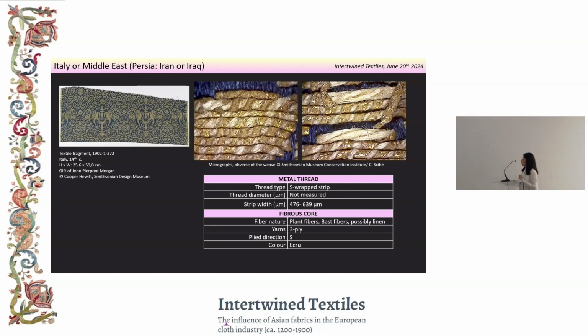So we have threads that are always made by metal in S-wrapped direction. So they were wrapped around a core made by linen fibers. The core was done with 3 yarns plied together in S direction. Sometimes we have found as well a core made by 2 single yarns, and just in one exception that we have studied, we found silk. So these little differences may be related to different workshops or different production areas. But we are still far from being able to define if they correspond exactly to Persian or Italian production.